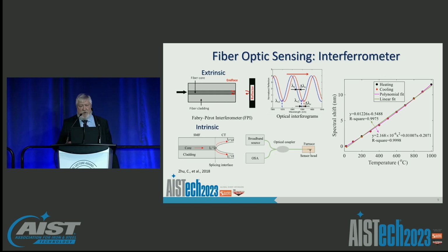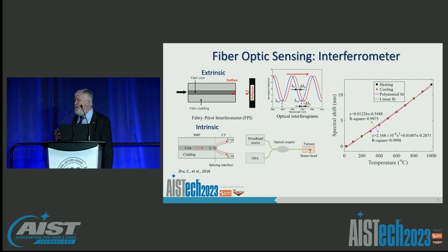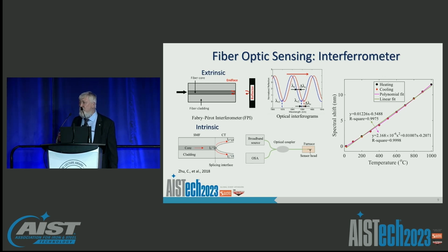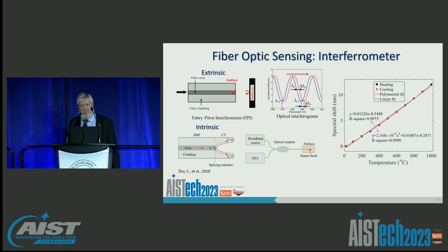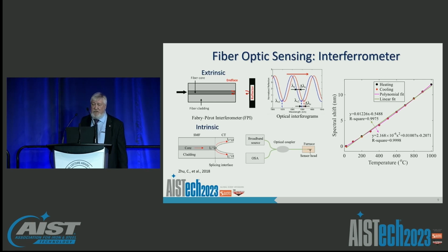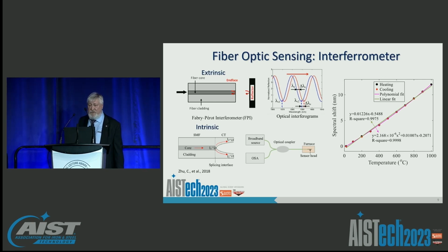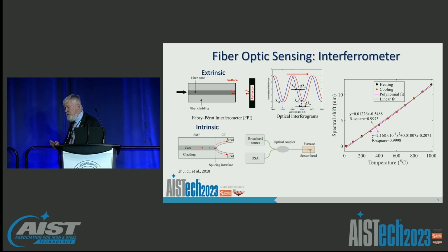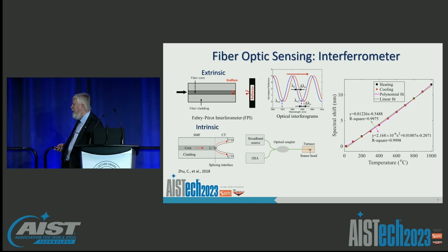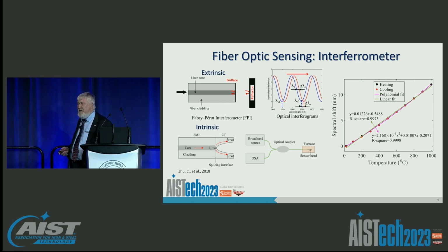So the other approach here with these types of sensor systems is that they're single point. They can be used either as an intrinsic fiber where the sensor is built in at the end, or you can have a reflection off of an external target. And the plot to the right basically shows how that spectral shift occurs as a function of temperature for a sensor that has an intrinsic interferometer. I'll show you some other examples where we can use these types of systems to actually measure the evolution of gap during solidification shrinkage, or even interrogate flux layers in the continuous casting process.